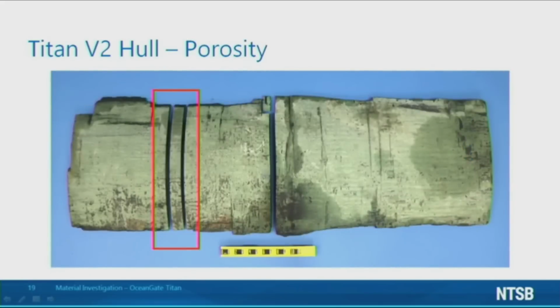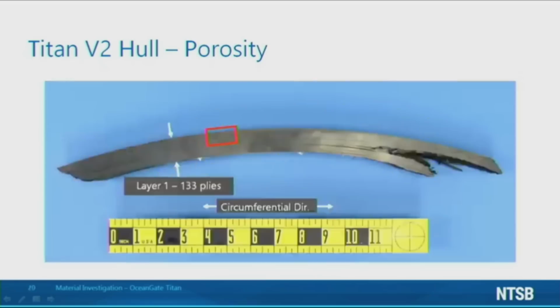We also observed porosity between composite plies. This is an image of a single layer piece of the hull that was retrieved from the ocean floor. The side that is shown is the adhesive used to join two layers. The other side is painted, indicating that it is the innermost layer, or layer 1. The strip has been cut out to evaluate the through thickness material structure.